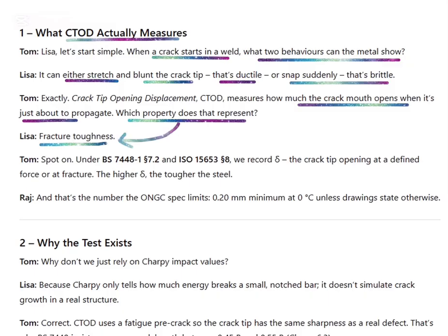That's fracture toughness. So under BS 7448 and ISO 15653, we record delta, the crack tip opening at a defined force or fracture. The higher the delta, the tougher the steel. And that's the number. Spec limit is 0.2 mm minimum at 0 degrees Celsius unless the drawing states otherwise.